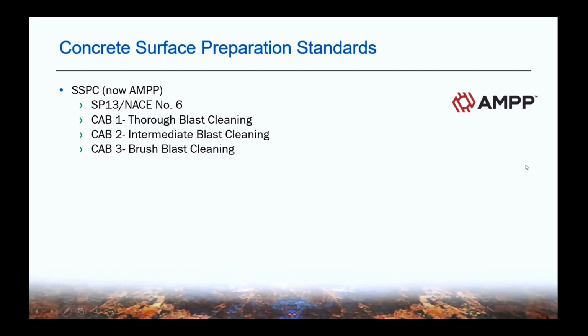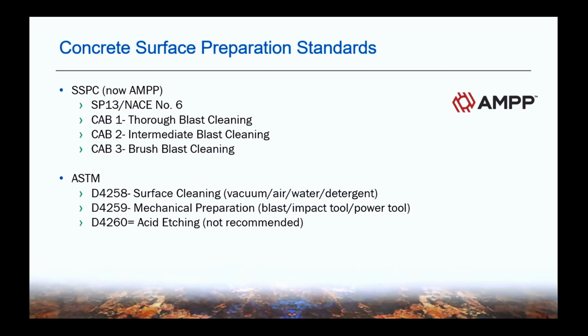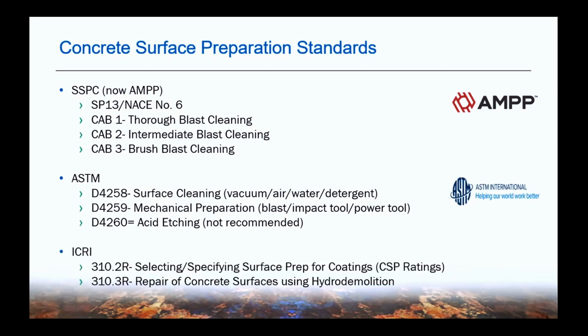I thought it was worth mentioning here some of the newer standards that you see, the SSPC CAB or concrete abrasive blasting standards. There's actually 3 levels of that, and these are written specifically to preparing concrete surfaces that will end up receiving a lining system in most cases. So when you're building a specification or reviewing a specification, there's also several ASTM standards that speak specifically to concrete prep, which are listed here. But the one I wanted to focus on here is the ICRI standard, the 310.2R, which does a great job of laying out the various concrete surface profiles, or CSPs as we refer to them. These are going to be called out typically before you apply any resurfacer, coating, or lining.